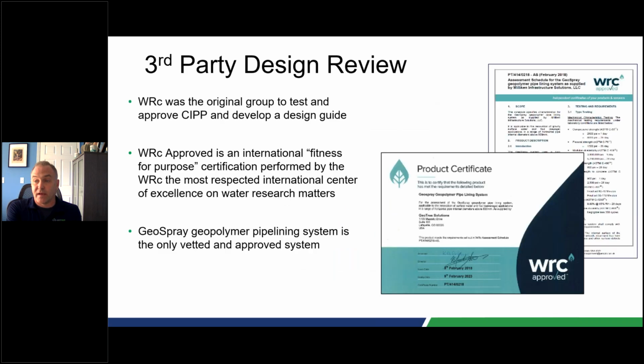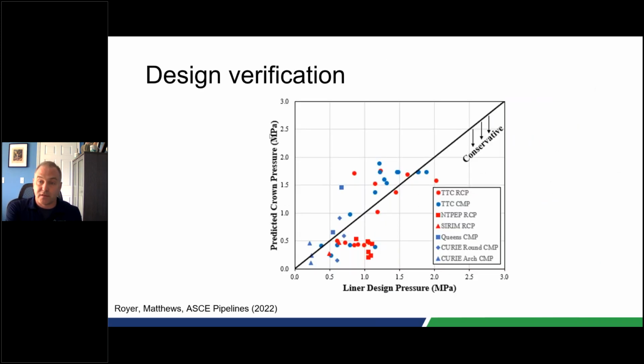What we normally tell people is, and these are in scientific units, 1 MPa is approximately 145 PSI. As long as the design pressure is below 145 PSI, you get a reasonable prediction that's reasonably conservative for your design. If you are above 1 MPa, there is a lot less conservativeness, so we would recommend doing a different type of design. But when you look at the design pressures applied to a pipe, there is no live load that you can legally use that would get you to 1 MPa or 145 PSI. You'd have to be 50 to 60 meters deep and be taking all of that soil pressure, which for a rehabilitation job where the soil should be reasonably arched is probably not a reasonable condition.